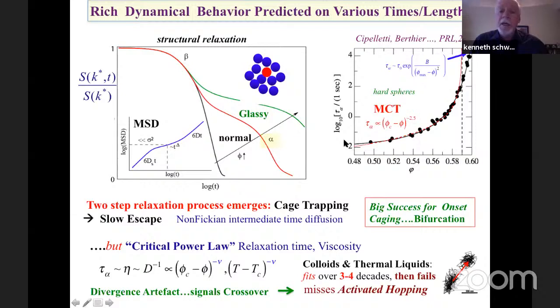The exponent is predicted. It just needs to be moved around where this divergence is. It can be fit to the data over about 3 to 4, maybe 4 orders of magnitude. And then it appears to disagree because the theory predicts a strict divergence without hopping and the experiments continue. So my belief, and I'm not sure anybody disagrees with this, is that the divergence is an artifact of the approximation and signals a crossover. And what's missing is the ability to predict rare, enormously non-Gaussian processes that at the single particle level we could call hopping.